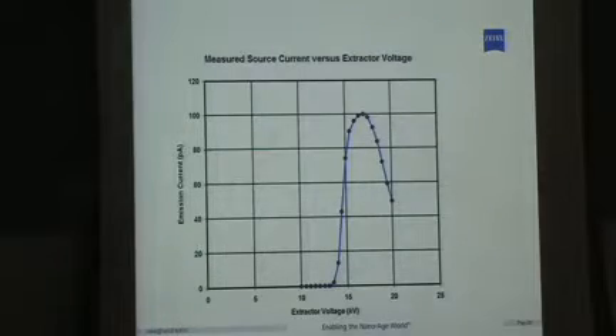So here, like any ion source or electron source, there's a voltage-current relationship. On the horizontal axis is the extraction voltage that's applied. On the vertical axis is the emission current coming out of that trimer. We call it those 3 atoms. And you can see at too low a voltage, you don't get anything. Your pattern would look like this. As you increase the voltage, you start to see this trimer emission. You're starting to pull in more helium. The electric field sucks it in towards the tip and helps to ionize it.